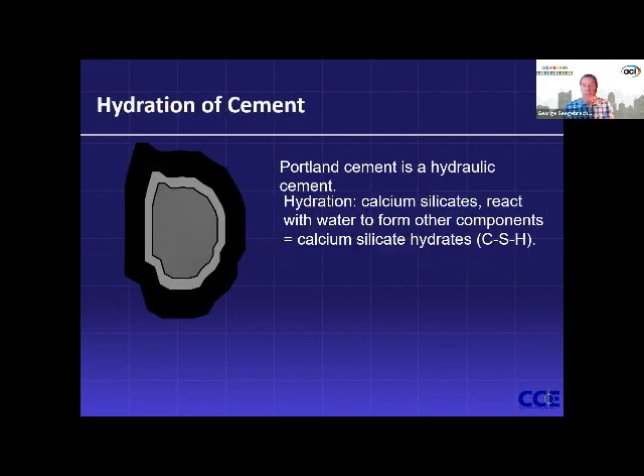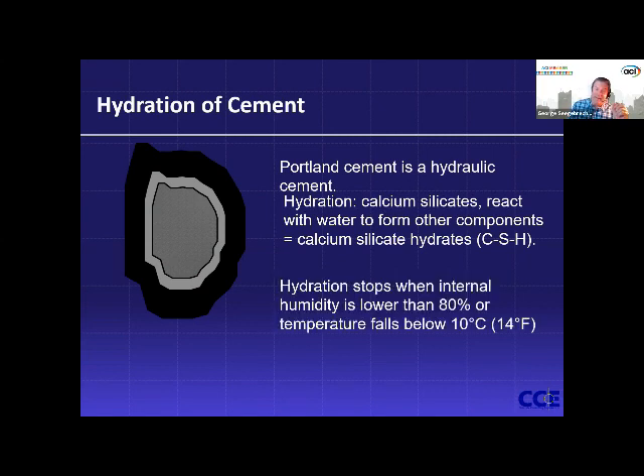This is a hydraulic reaction, just to go through the basics, where we are trying to supply water to these cement grains so that they can hydrate. That produces calcium silicate hydrates. As long as you keep the temperature and the moisture favorable, it'll continue. If you start dropping below a relative humidity of about 80%, or a temperature down to 14 degrees or less, the hydration process essentially stops.